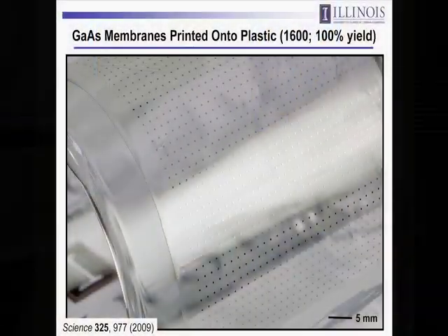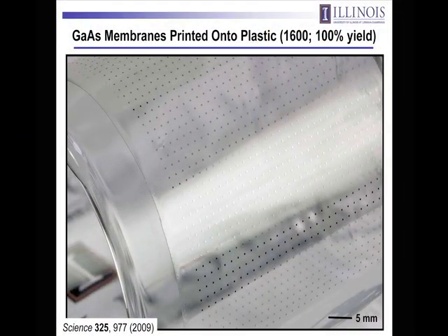So this is a sheet of plastic, a PET. It has on its surface a square array of square gallium arsenide nanomembranes, about 250 microns on the side, about 200 nanometers thick. It's about 1,600 of them in this particular case, with 100% yield. Starting from a dense array of these things, undercut etched, strategically anchored on a mother substrate, and then assembled in this step and repeat fashion to create a sparse aerial coverage on this sheet of plastic.